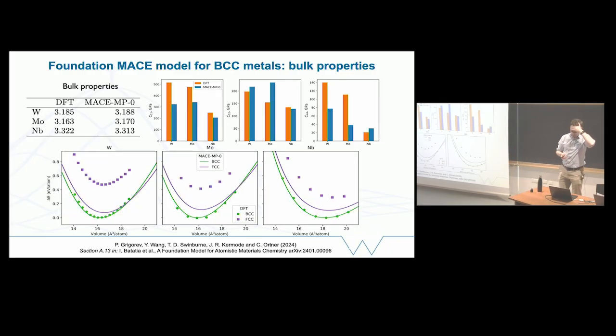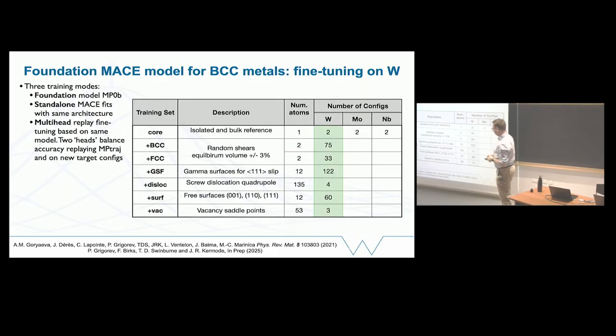The thing that went a little bit wrong is it had never seen any FCC configurations at all. So everything in the Materials Project is in its ground state. If you have tungsten, it's in a BCC state. That means it doesn't really know the energy difference between the BCC and the FCC. And you might well need things like that for the reasons that I referenced right at the beginning of the talk, where you have local transformations and you need to be able to describe a range of environments. So that was what we set out to try and fix.